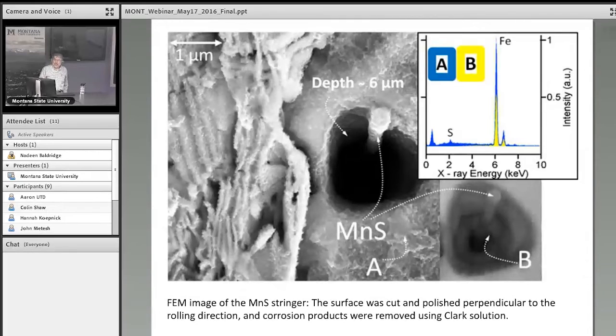Again, here is a manganese sulfide. I have two messages with respect to this graph. Actually, maybe three messages. First of all, if you use electron beams about 1 keV in your imaging, you get very high resolution. Very fine surface detail can come out. But you don't see deep holes.